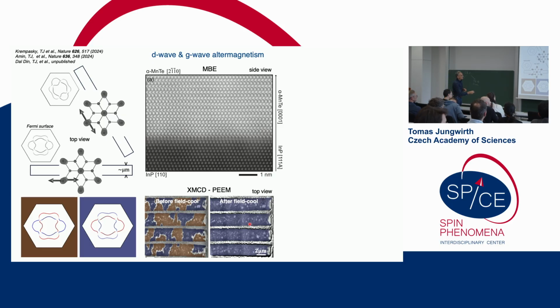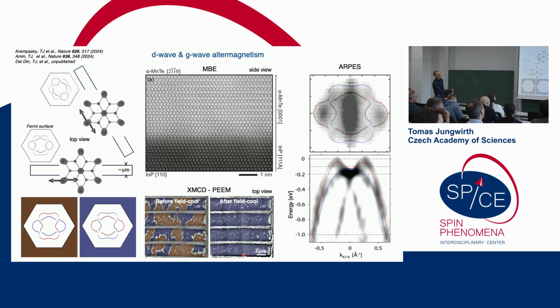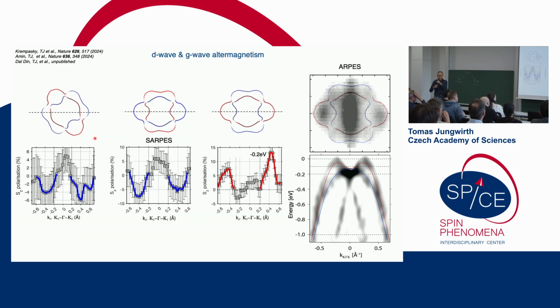And now the thing that I would like to emphasize is that at the end of the story, they get these very clean ARPES Fermi surfaces and also band structures. But the absolutely remarkable thing, to me, is that from here to here, they did it without breaking vacuum. And this is what you really have to do if you want to do high resolution spin resolved ARPES: have surfaces as perfect as possible. So from the growth, including the patterning, including the field cooling, all the way to the ARPES, the high vacuum has never been broken. Which also means that you have to grow in MBE on already pre-patterned substrates. This is regular ARPES, and this is spin resolved ARPES. Okay, so final slide.